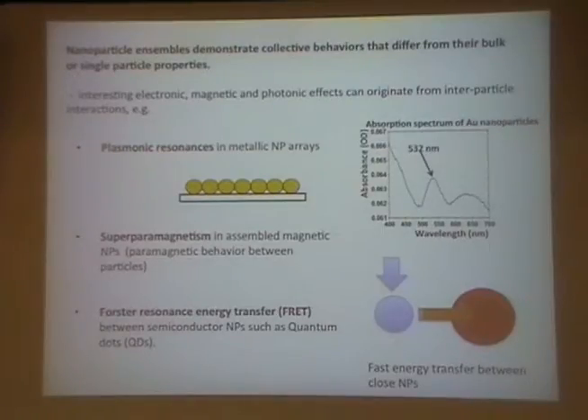So some examples of how clustering can give different effects are plasmon resonance in gold particles. If we have lots of gold particles together, we can observe plasmon resonance. And here we can see one we actually measured in our lab. There's some gold nanoparticles. Superparamagnetism, that's an effect where we can have a paramagnetic-like system when magnetic nanoparticles cluster together. So that could occur at room temperature.